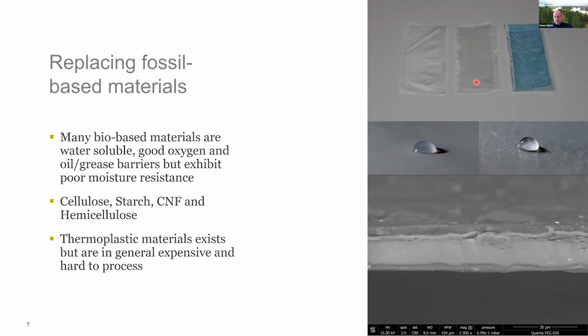Whereas if you put a water barrier on top of it that is hydrophobic, you can see that you have a totally different shape of the drop. It's more or less water repellent, and you don't have the water dissolving into the film here. This is actually a cross section of this film, where you have the barrier layers on each side and the nanocellulose in the middle.